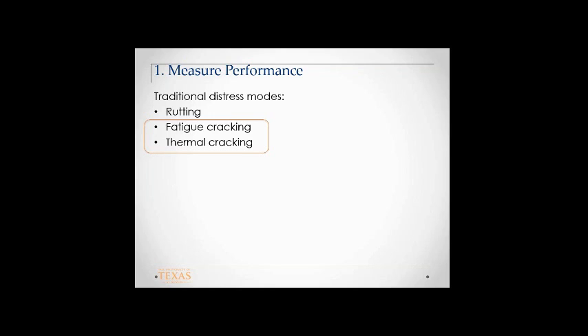In terms of fatigue and thermal cracking, again, aggregate structure plays a role, but at the end of the day, it is the binder that has to take the responsibility to resist those tensile stresses, if you will, in a very simplistic fashion. The same goes for thermal cracking, in that ultimately binder is the material in an asphalt mixture that will relax and relieve those stresses when you have a nice cold weather outside and the temperatures are dropping.